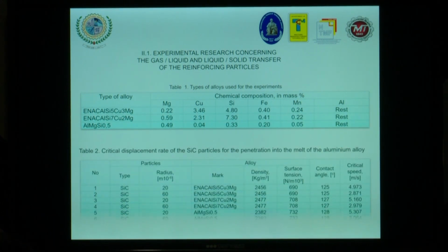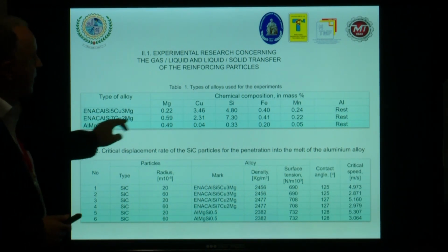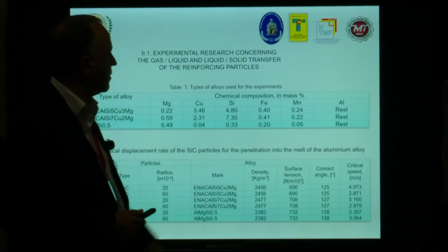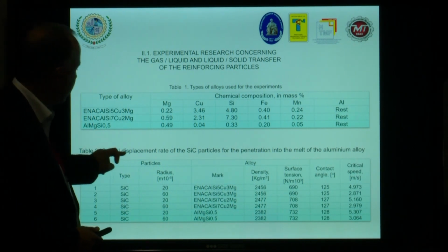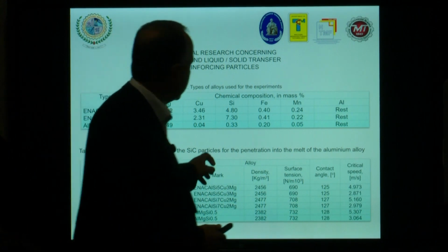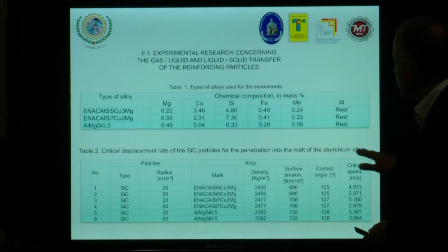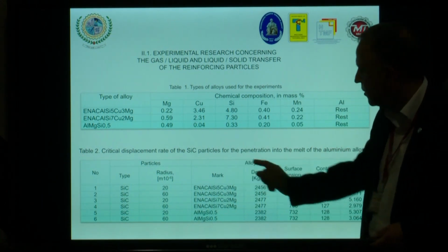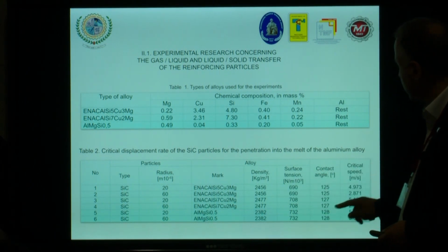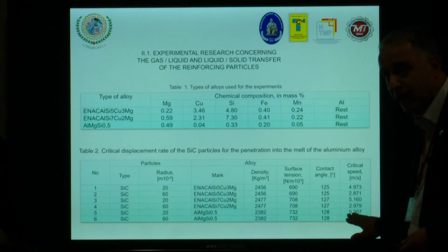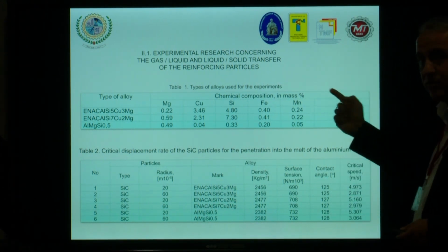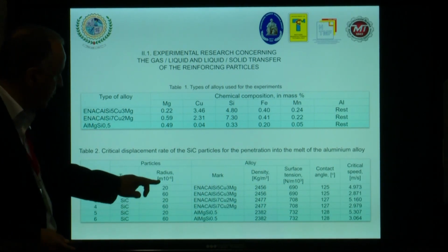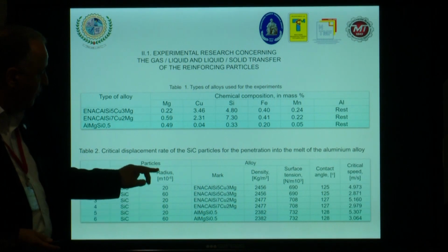And now a little bit of information about the experimental results concerning the gas to liquid and liquid to solid transfer of the reinforcing particle. We used 3 types of alloys. The chemical composition: magnesium, copper, silicon, and so on, manganese, aluminum the rest. Another one, the critical displacement rate of the silicon carbide particles for the penetration into the melt of the aluminum alloy. You can see all the information, including the density, surface, contact angle, and the critical speed. So we made all the calculus for the critical speed, taking into account the relation that we already presented. Also, you can see the radius, 2 levels, 20 and 60, for the particles.